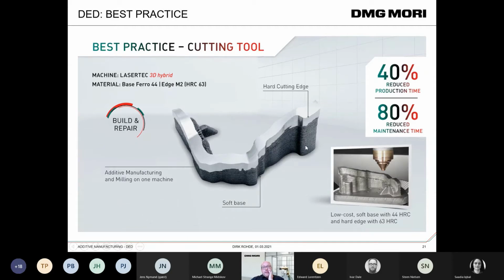This one is extremely fast. It's a cutter knife repair setup of the machine. They print the soft base with the tool steel Ferro 44, which comes out at 44 Rockwell, and then you have a so-called M2. That's a high-speed cutting steel. Typically, you cannot weld high-speed cutting steels, but it's available as a powder and works great in the machine. So we have a 2 millimeter hard layer on this knife that comes out of the machine at 63 Rockwell, ready for installation into the tool back again.